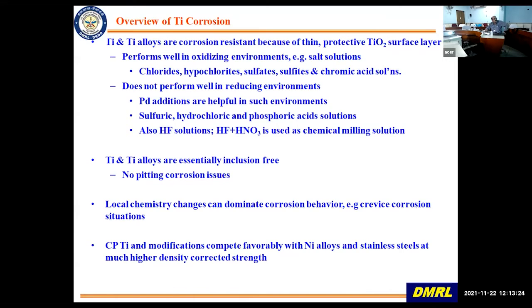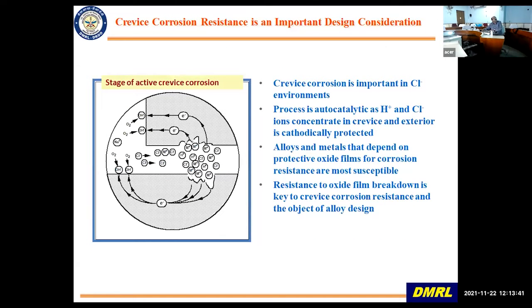And CP, commercial purity titanium, with additions like palladium, etc., all compete very well with nickel based alloys and also stainless steel, etc., as far as density corrected strength is concerned. But the titanium alloys are quite prone to crevice corrosion.